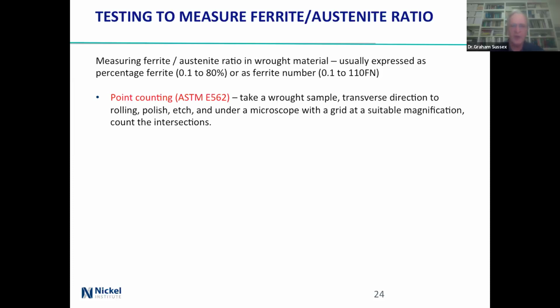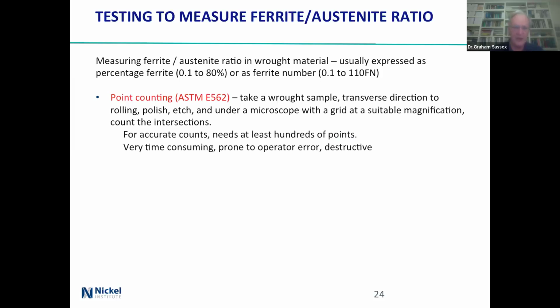If you're looking for the ferrite-austenite ratio in wrought material, it's usually expressed as a percentage ferrite. That'll be 0.1 up to about 80, or a ferrite number, 0.1, sorry, up to 110. They're not the same. I'll give you an example of what it means. And you can do it several ways. ASTM E562: you take a wrought sample, you do a transverse direction to the rolling, polish it, etch it, put it under a microscope with a grid. That can be a circular grid or a square grid or whatever, and count the intersections with the particular phases that are there. You're going to need hundreds of points if you want to get lots of accuracy, very time consuming, very prone to operator error, and it's a destructive test and it's slow.